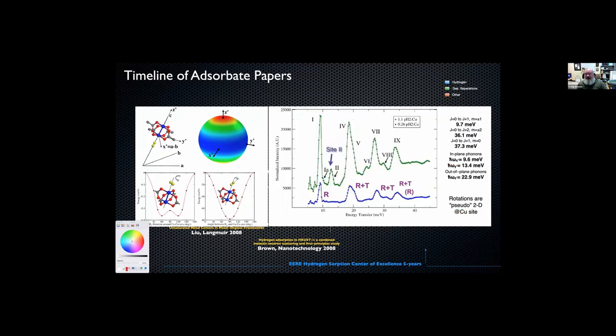And so we can assign each of these transitions, if you just compare to the blue again, to rotation and rotation-translation coupling. But it doesn't agree very well with what you'd expect for a simple one-dimensional or two-dimensional potential system that's often used in the literature.